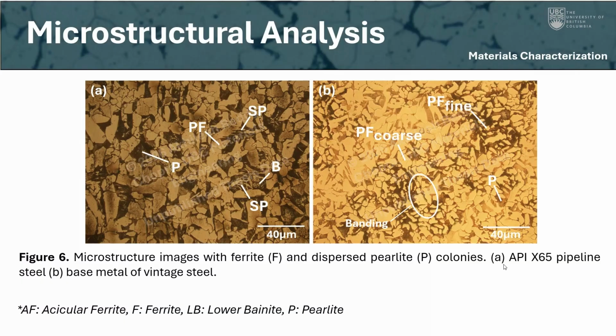Okay, so in this image, we can see the microstructure of both image A in the X65 steel and image B, our vintage steel. So note in image A, we see a relatively uniform distribution of polygonal ferrite. Also with some areas, if you look at the pearlitic phases, we see bainite as well as some needle-like or side plating of ferrite pearlite. So this is also known as Widmanstätten ferrite. And this can also increase the strength of our steel, but of course that has to be well distributed, which we can kind of see from the morphology of image A.